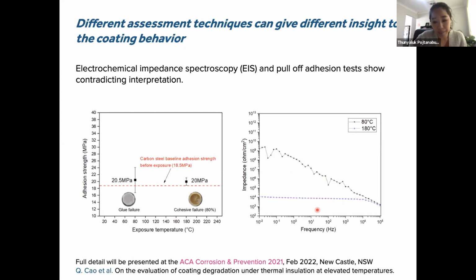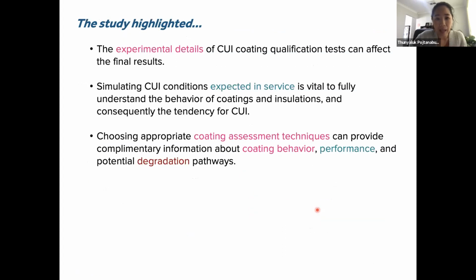So we're still looking at different types of assessment techniques. But what it shows is that the selection of the coating qualification test is important. It should simulate the CUI conditions expected in service. So if it is going to be used with insulation, and with different types of insulation, that coating should be studied in conjunction with that type of insulation material, and we should use a more appropriate and more comprehensive set of coating assessment techniques to obtain different parameters and properties of the coating, to be able to understand the coating behavior, performance, and the degradation mechanism of that coating.